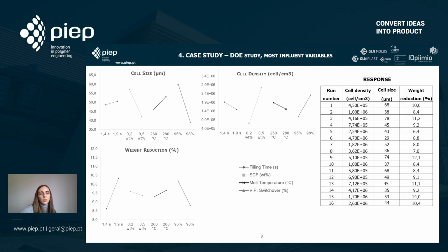So here what we can see is that 95% filling of the cavity is better to achieve high results for weight reduction, which makes sense because we're filling the cavity with a lower amount of material and letting the gas expansion fill out the rest. However, we can see that if we do this, we will have lower cell density and lower cell size. So this is why it is important to always analyze these three results together, because at 95% we will have, near the weld lines, probably a cell size bigger than it is near the gates, and we will have different mechanical properties throughout the part.